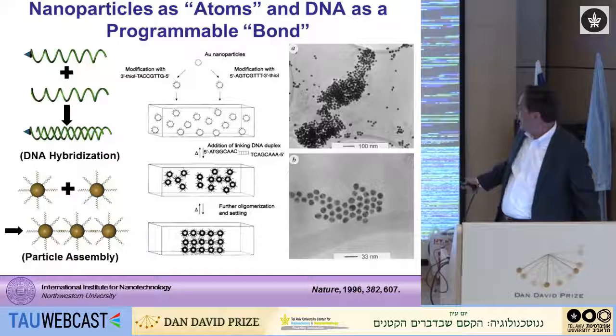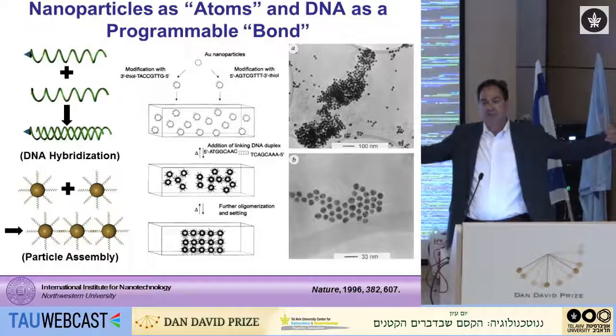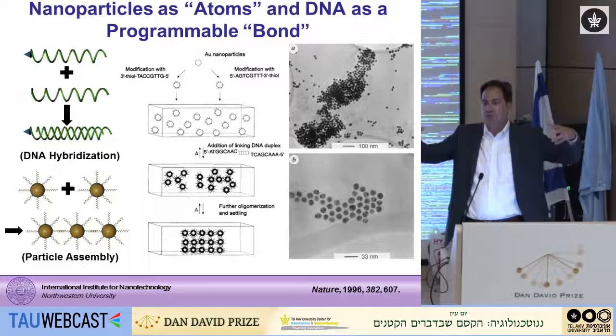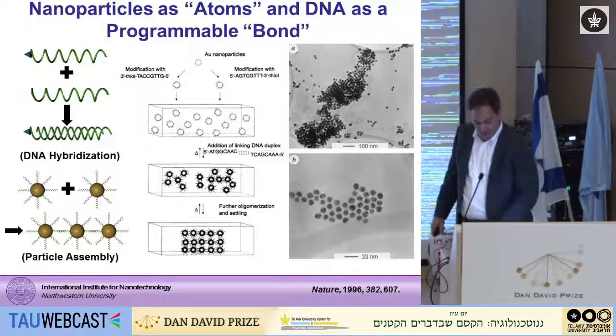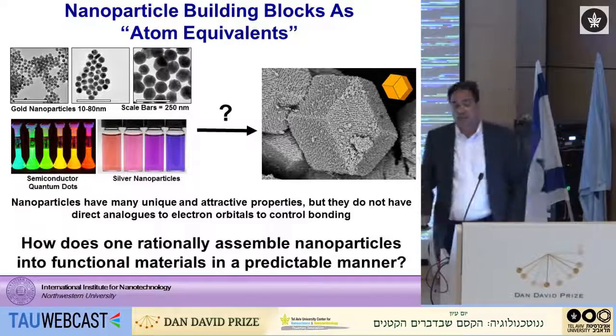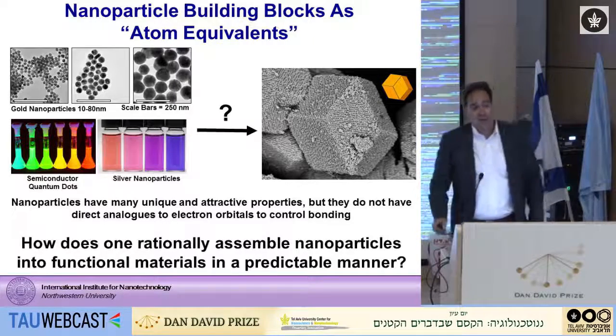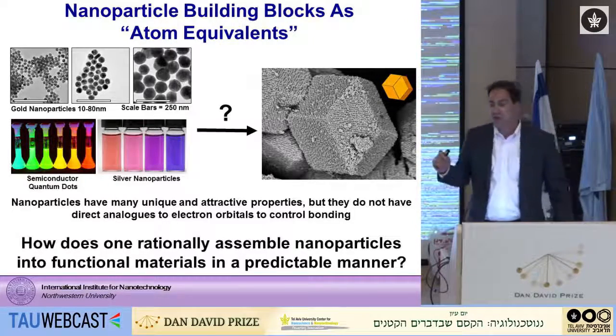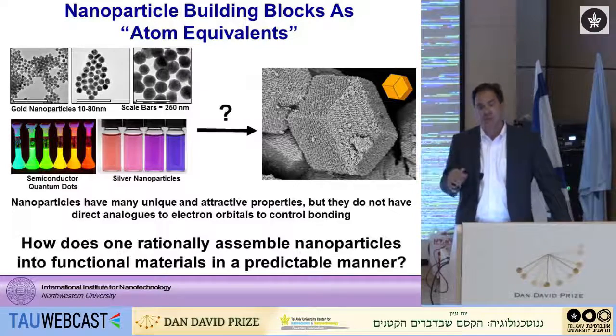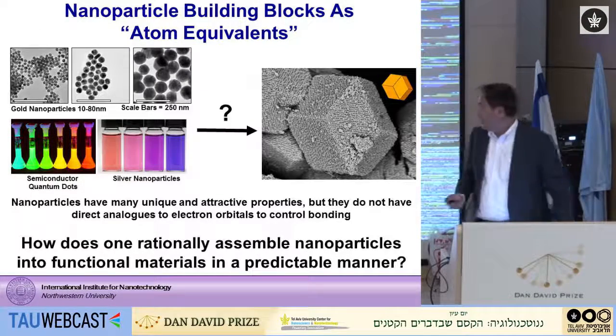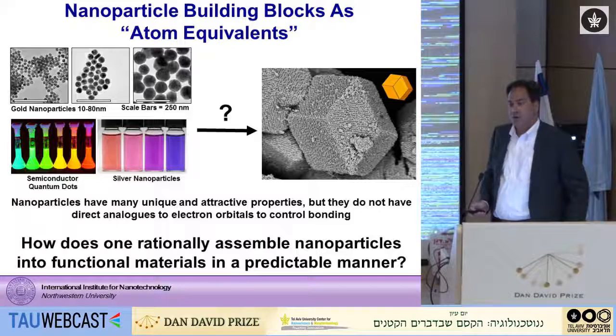In fact, looking back at this, these are actually not the connected structures under the electron beam. These are the particles that are left behind after they dehybridize. But they give you at least a snapshot of what you had, which was kind of an amorphous aggregate of particles. Well, today, we make these types of structures. And we've learned how to do this because we spent a lot of time studying what's important in this particular area. And it really builds off some of the themes that Paul introduced, this idea of kinetic versus thermodynamic control.